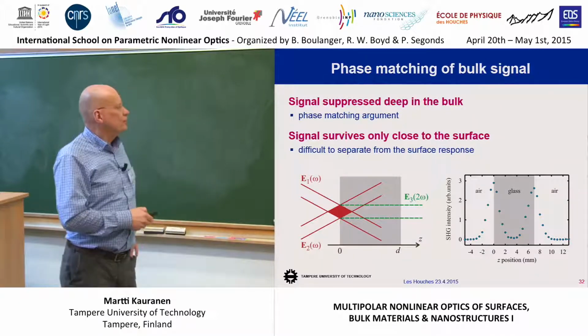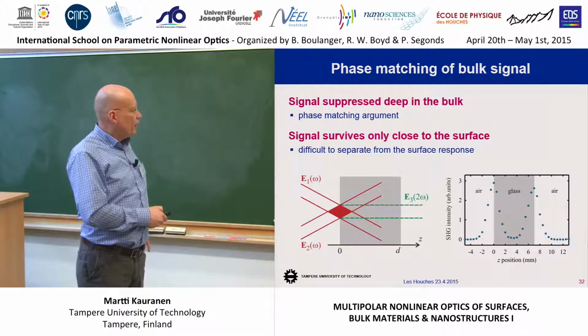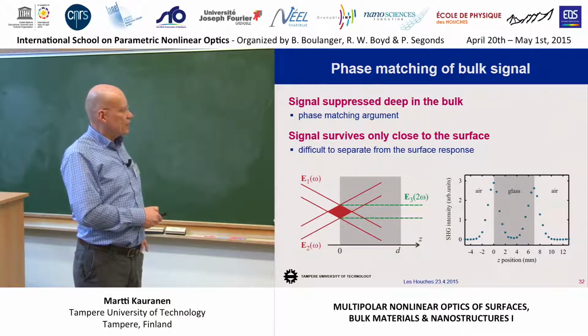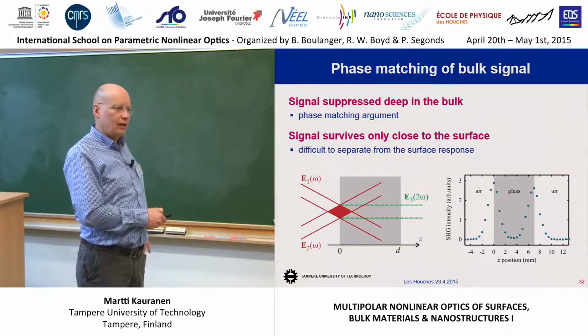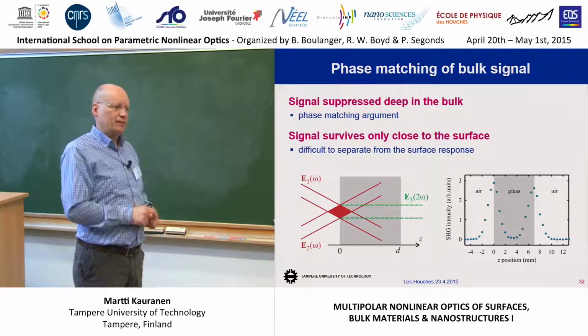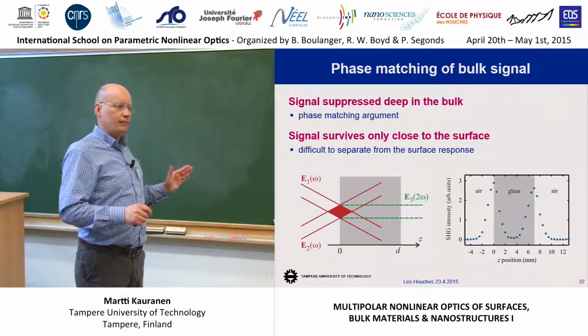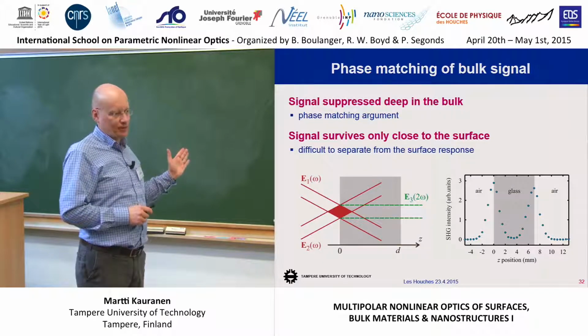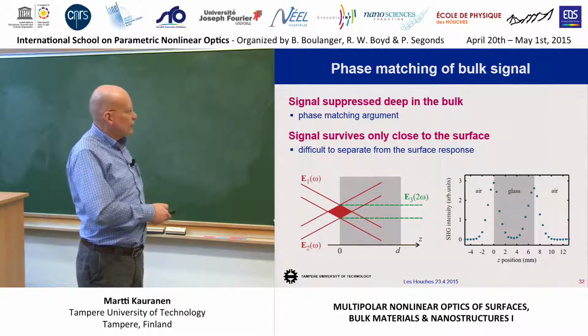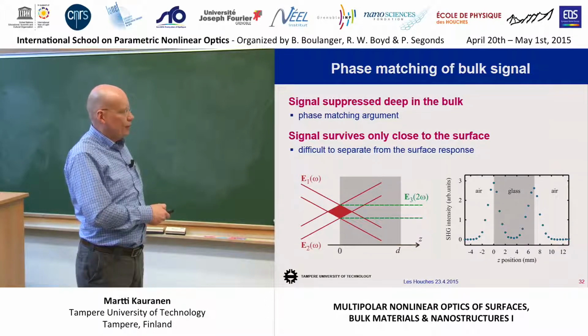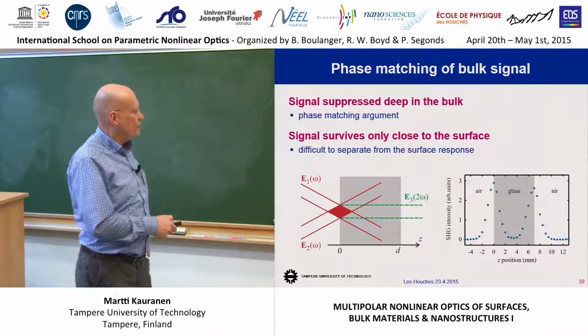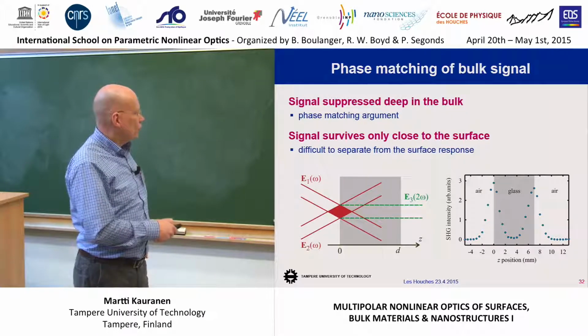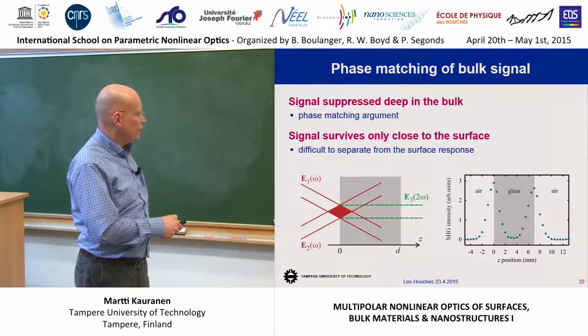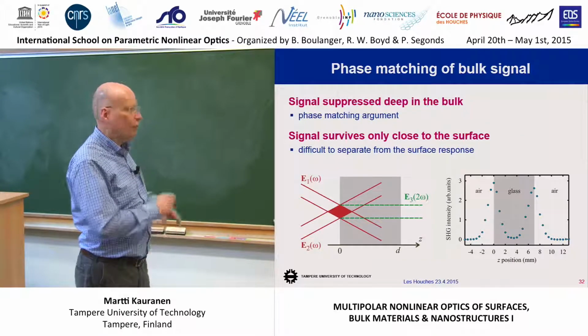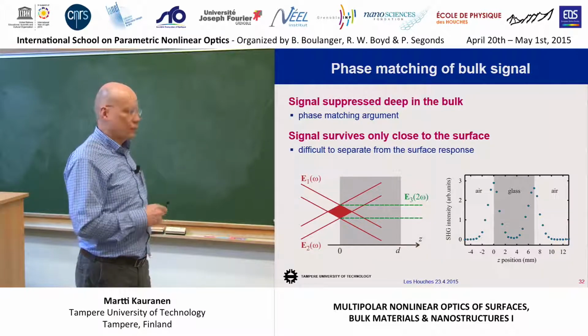Then it turns out that when we work out the details, if you localize this interaction region deep into the bulk, in order to access only the bulk response, your integrated signal is 0 because of phase matching reasons. So you have to bring this interaction region close to the surface. The reason you get cancellation deep in the bulk is that what you get from this triangle here exactly cancels with what you get from here. So the two halves get out-of-phase contributions.